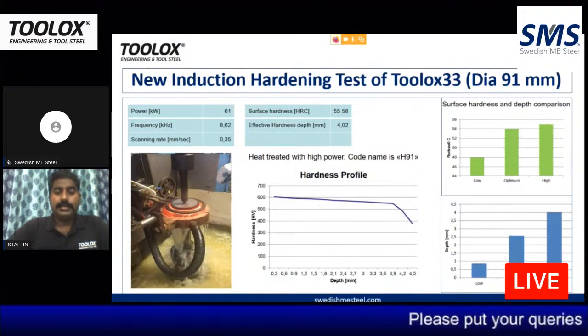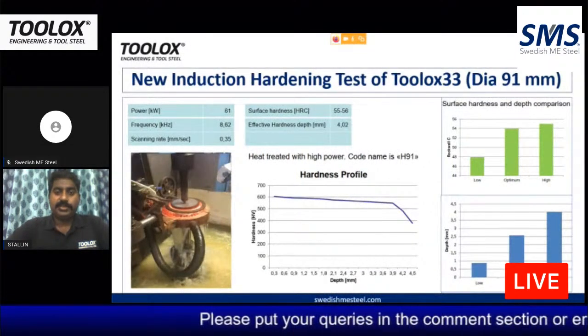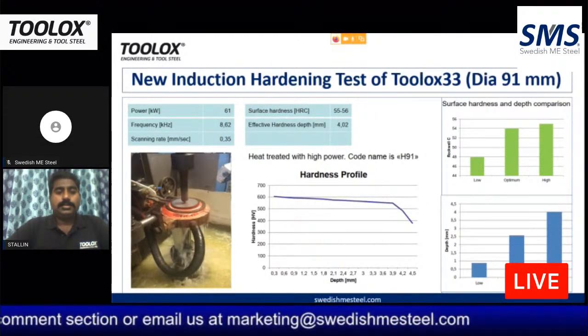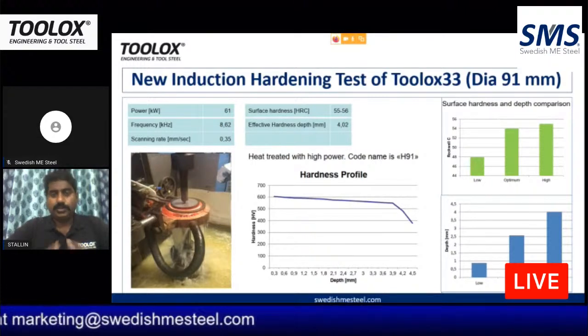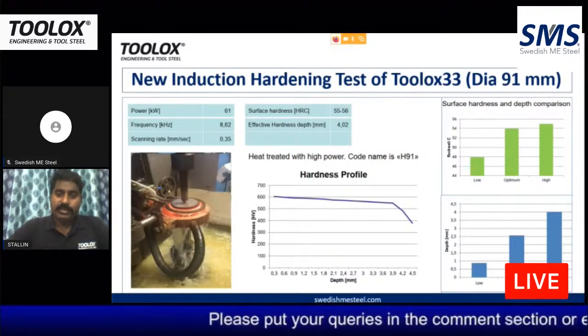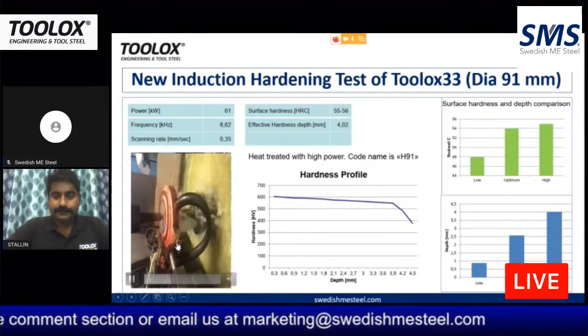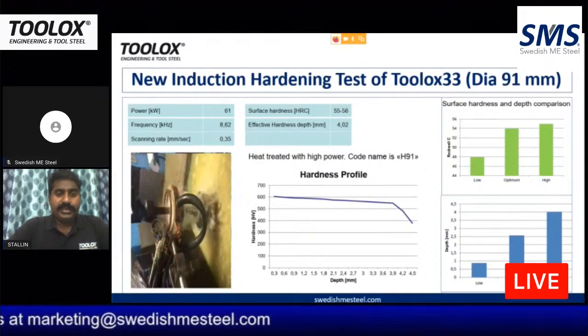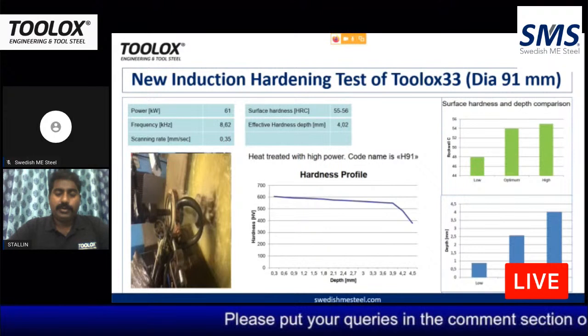We have also done induction hardening on both the grades, and surface treatment is possible. That's the added advantage. You would find that the normal P20s would not stand up to these kinds of treatments. So Toolox is much better prepared for all the external pressures that you put on the material. This is a Toolox 33 dia 91 material, and this is how the induction hardening is done. You can find the effective hardness depth is 4.02 mm in this particular item, and the surface hardness achieved is 55 to 56 HRC.